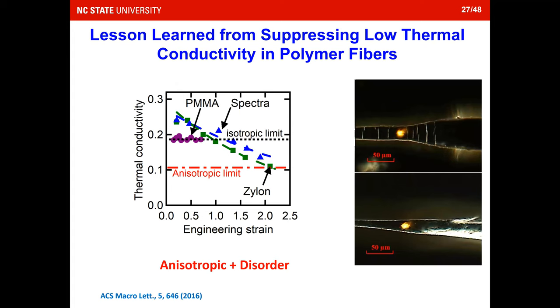So we also learned from the polymer fibers. Seems like I'm pretty obsessed with polymer fibers to get fundamental insights. Polymer fibers are a very anisotropic structure, right? In the fiber axial direction, you have pretty aligned polymer chains, and in the radial directions, you just have those van der Waals forces. So we first tested the PMMA fiber, which is a purely amorphous fiber. It's not surprising that PMMA just has the regular 0.17 thermal conductivity, which can be completely described by the isotropic limit. So it's already in the limit.